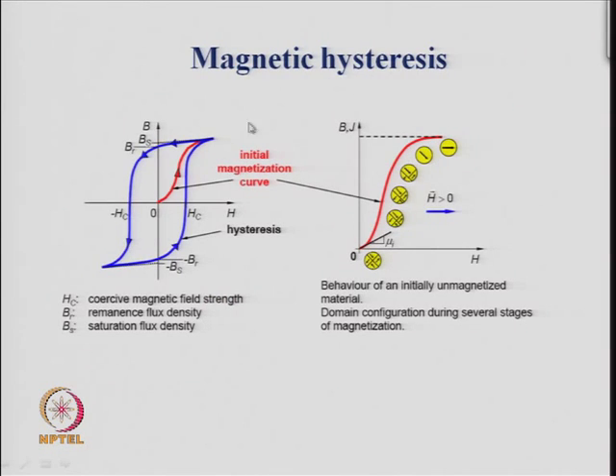So, if you look at the hysteresis loop again carefully, the red line shows that initially you started with 0, you reached the maximum which is possible magnetization, and here we are plotting it in terms of the flux density, which is related to the magnetization. So, you can plot the flux density also, and so you have a remanent flux density Br, and then you have a coercive field, and this kind of plot shows you a ferromagnetic substance.